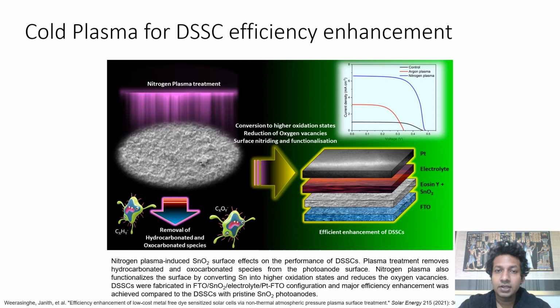The increase of the current density mainly causes the enhancement of the performance of these dye-sensitized solar cells. Therefore, it can be attributed to the increase in the number of electrons transferred from the sensitizing dye to the conduction band of the tin oxide layer. This might occur due to the increased dye adsorption to the tin oxide surface as well as the elimination of trap sites in the photoanode.